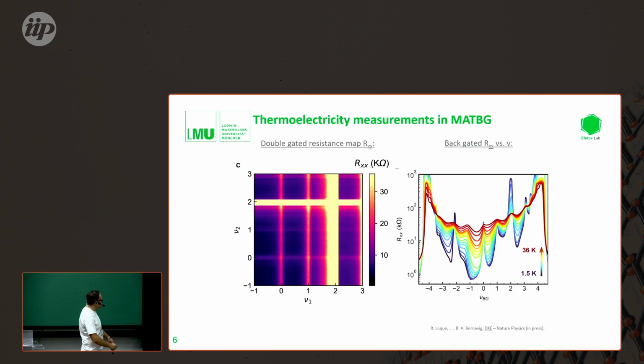Okay, so basically this is our device. Here is our Rxx as a function of filling. So we see gap states appearing at filling factor 2 here and -2. And generally, this is a typical twisted bilayer graphene device that we can have. And now what we can do is plot this resistance as a function of the left region of the device and the right region of the device, which correspond here to the different axes. So we can create this imbalance between electrons and holes.